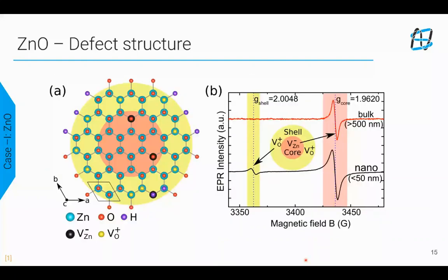And this distortion is the reason behind the change in properties, so manipulation of properties can be done by changing the intrinsic defects, or while you are synthesizing the material itself, you can modulate your composition or sintering conditions to modulate the intrinsic defects. So what you're seeing here is a small nanostructure, unlike a supercell, meaning a few primitive units arranged in space with several defects that you're seeing. So what we did here is electron paramagnetic resonance to see if you can see the vacancies via this technique.